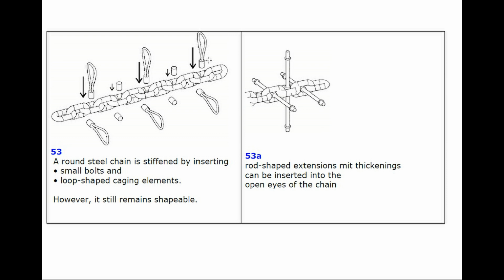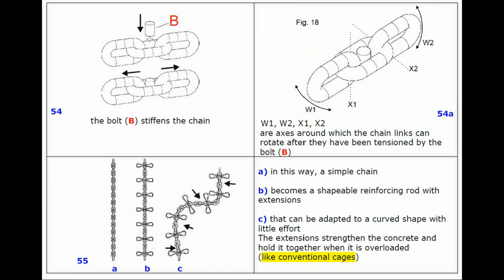We have different kind of extensions with loops or only rods with a thickening at the end. The bolt is put into the hole of the chain, but the chain is then not easy to bend. It's difficult to bend. There's a lot of friction around the axis because of connecting metal onto metal. In an illustration here you see the simple chain. It becomes shapeable reinforcing rod with extensions, and that can be adapted to a curve, whatever you want.